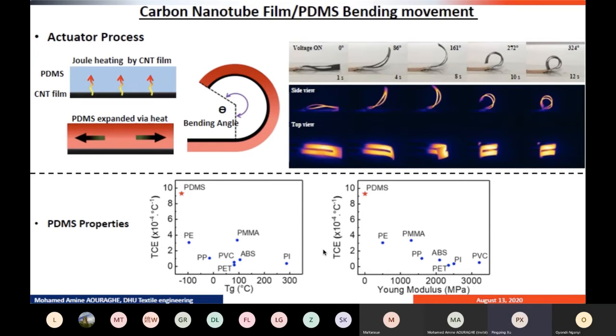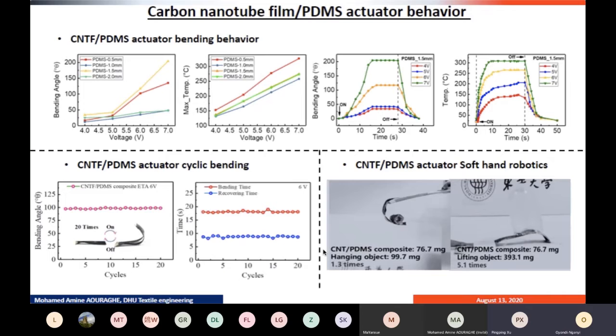In our study, we have plotted CNT film with different PDMS thickness and studied its effect on the mechanical bending behavior according to the different applied voltages. As we increase the voltage, the resulting bending angle of the actuator increases systematically, and the converted temperature increased simultaneously too, as shown in this figure. However, PDMS with a thickness of 1.5 showed large deformation, corresponding to the optimum amount of the polymer to get optimum actuation for the designed actuator.